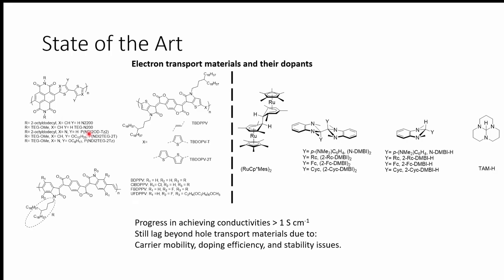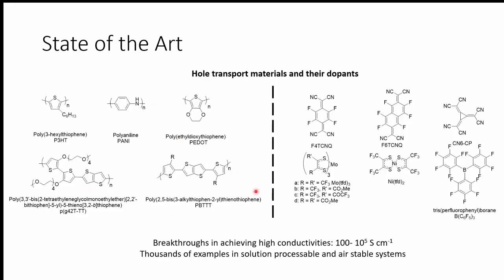So when you add an electron into a molecule, molecules tend to not like it, because normally that puts it into the LUMO, or the conduction band, and that is very susceptible to oxidation by air. And you see all of these scary structures, but these are all permutations that people have tried to achieve some high conductivities. And although, if you go back on slide, we talk about 100 to 10 to the power 5 in terms of these materials that we can oxidize.